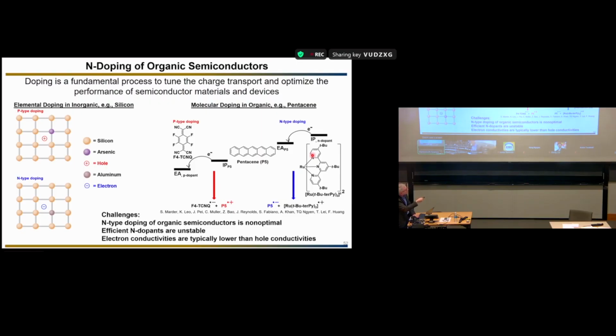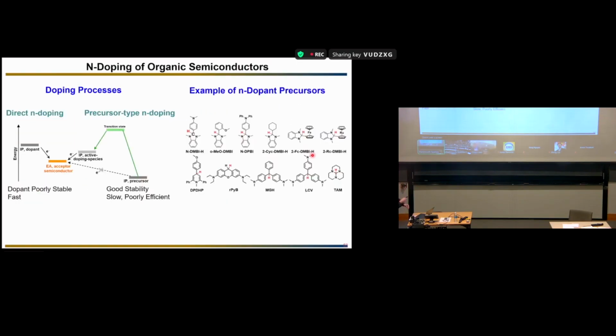The major issue for organic is that this process is usually easy. You can easily p-dope organic, but the electron doping is much more difficult. And it usually does not occur by having a molecule which transfers the electron directly. Usually you use what is called a precursor dopant. So it means you use a molecule which itself does not have the energy to transfer the electron.